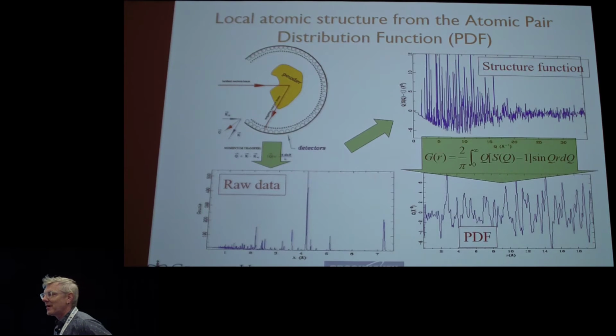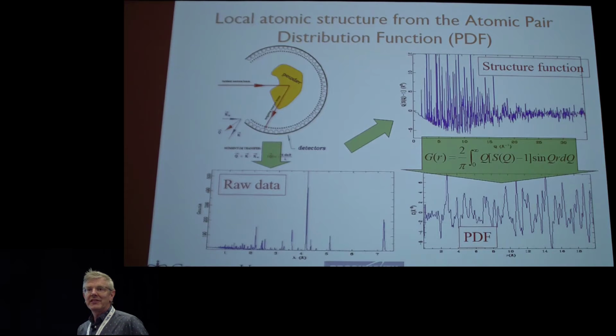All right, so coming back to the PDF, how do we do the PDF? So the PDF is actually just a powder diffraction measurement. We put a powder in the beam, we bring a high energy beam in, it diffracts off the sample and we get a powder pattern. And this is actually a powder pattern from a crystalline material, so we get Bragg peaks here. And then we make corrections for the instrumental effects and other experimental effects, and we do some fancy normalization, which I'll mention in a sec. And we get what's called the total scattering structure function. So this is just basically the diffraction pattern.